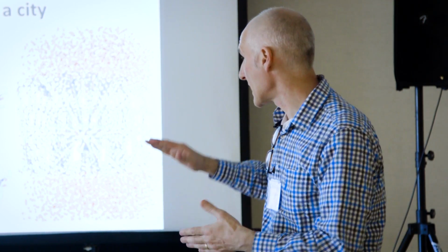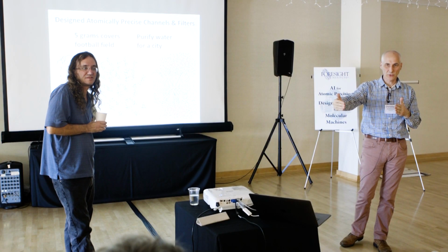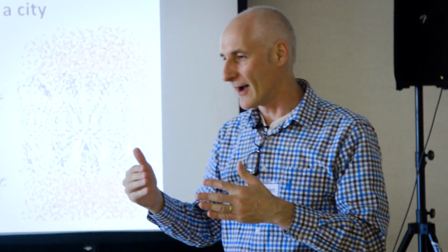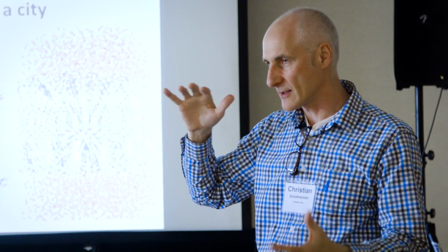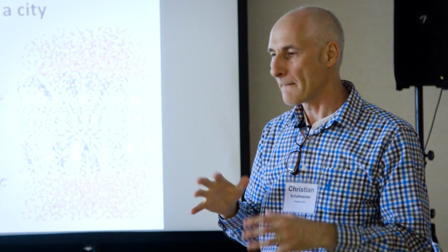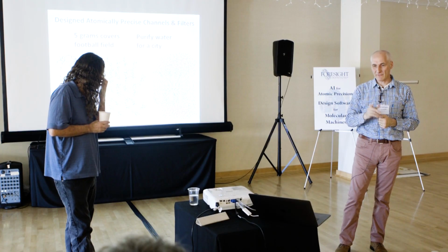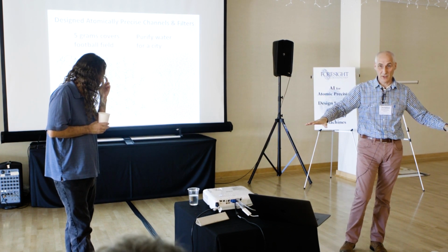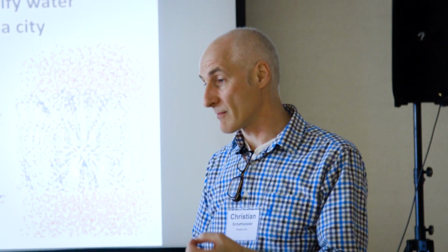We have the synthesis of these are all sort of convergent. So we synthesize segments and then we link them together, and we try and keep the number of linear steps short because you lose every time you do chemistry. This is one of the tragedies of chemistry. And I think we can assemble large molecules that are 5, 10 kilodaltons fairly straightforward. Beyond that, it's more synthesis. For membranes, this stuff really scales. I mean, 5 grams of this stuff would cover a football field of membrane. Catalysts, if you make active catalysts, a small amount can generate a lot of product.